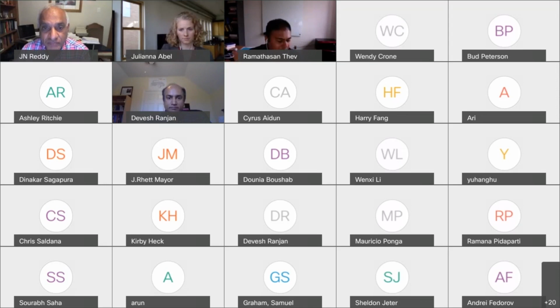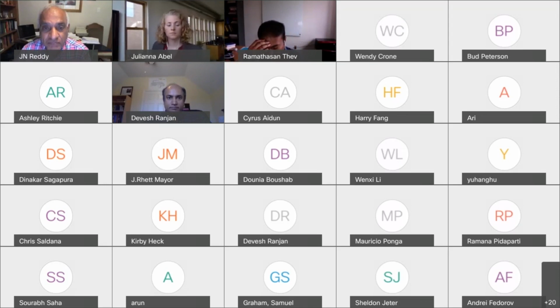Right. So this is another problem that I'm talking to one of our colleagues in the department, Dr. Kurt Bronkhorst. He studies these types of metallic systems in impact and high strain rate deformations. So we are trying to develop such things, but the models have to be developed such that we capture both the phase transformation and the grain refinements associated with that. That is something we have to do in a consistent fashion. But for the polymers, we haven't tried anything so far in the continuum approaches yet. So as you suggested, we need to incorporate this material characteristic length scale into the problem to do that. So there are a couple of questions from the audience.